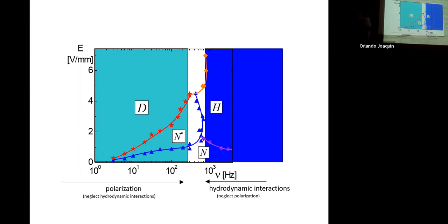Is that clear? The thing is I cannot hear you very well. So we did these experiments also at higher salt concentration to verify whether this mechanism that we propose is correct or not. And if it is correct, and you increase the ambient salt concentration by hand by adding salt, then this phase diagram could disappear, because the contribution to the ionic strength from the dissociated ions will become so small that it doesn't have an effect anymore, right? Okay, I think so.